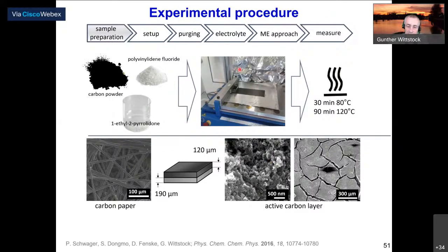I have sketched here a process to make such a gas diffusion electrode, which was actually done at the Fraunhofer Institute in Oldenburg. It's based on a carbon paper, which is then coated with a catalyst layer, heated and dried. And then the question is, what species do we form if we make the oxygen reduction in such an organic electrolyte?